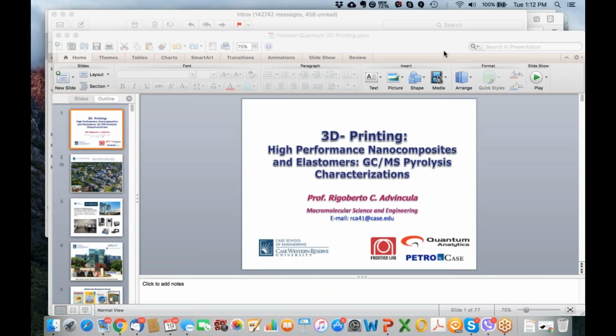Thermoplastic elastomers would be that of your SBS rubber or even polyurethane thermoplastic elastomers, having more compositions, again, of polyol and your hard segment, the MDI, TDI, or various aromatic isocyanates. So I would say it's a combination of the thermomechanical properties, the chemistry you're familiar with in the product, and of course, confirmation by GC mass spec pyrolysis. It's not possible to use GC mass spec pyrolysis alone, especially if you don't know the chemistry behind or have a clue on what could probably be the best composition of the product that you have.